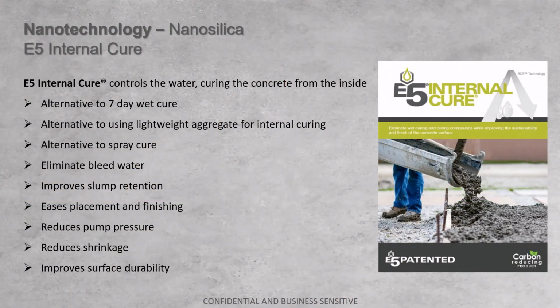These are grown silica particles that are put into suspension. They're functionalized, and they have particle sizes of between 1 and 100 nanometers. So these are particle sizes smaller than what we've previously put into concrete. Essentially, they were bolting on and using the E5 internal cure product, which controls the water and cures the concrete from the inside out. It could ultimately be used as an alternative to lightweight aggregate.